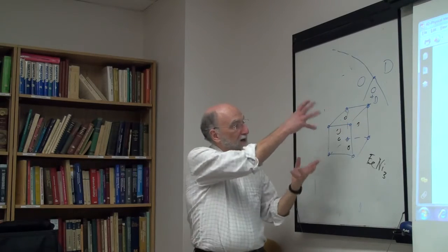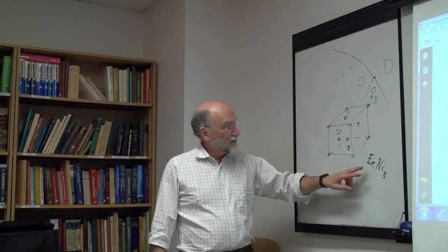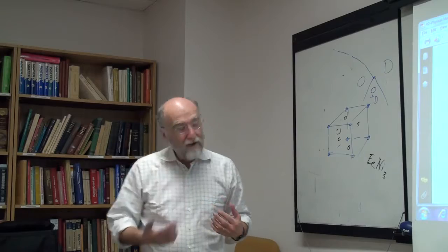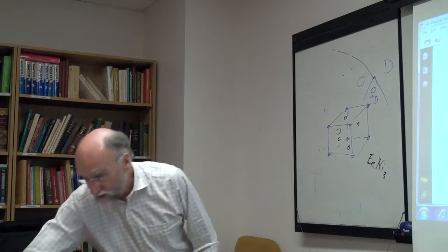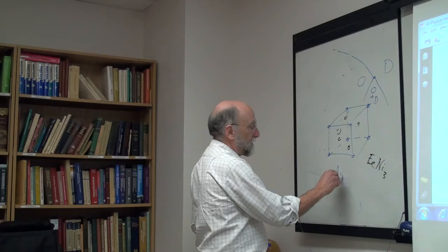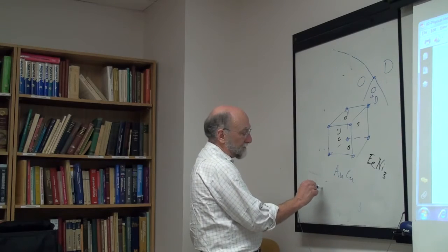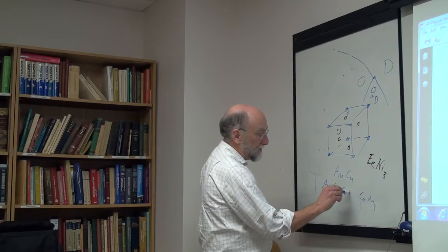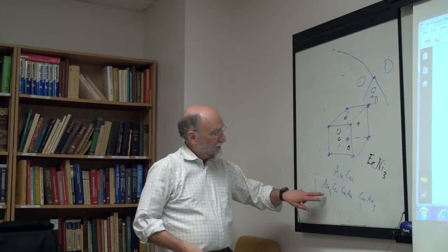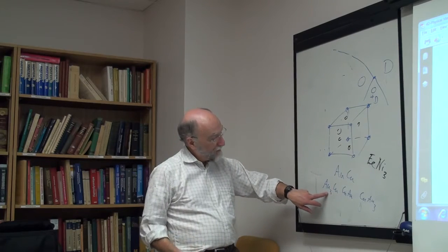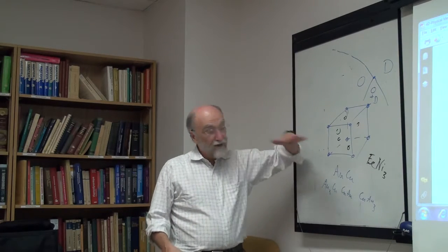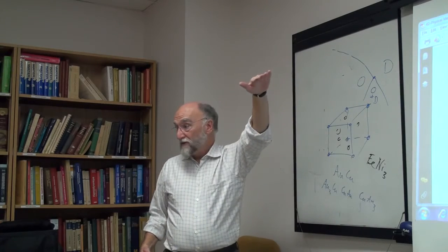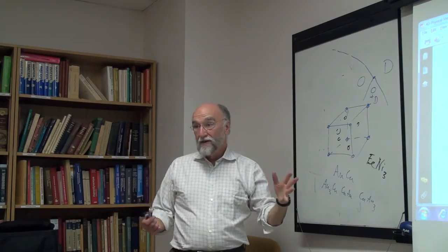And this is really important as to how these things distribute themselves, especially with something like FeNi3, when you can have three types of disordering, which is really all the same material. If you take the gold-copper system, you can have AuCu3, you can have Cu3Au, and you can have a CuAu, which are different. This is all the corner sites occupied by copper and the gold on the face center. This is vice versa. These are alternate planes, and when you go up to the disordered region, it's just one big face-centered phase. So you've got to treat the whole thing as one phase.